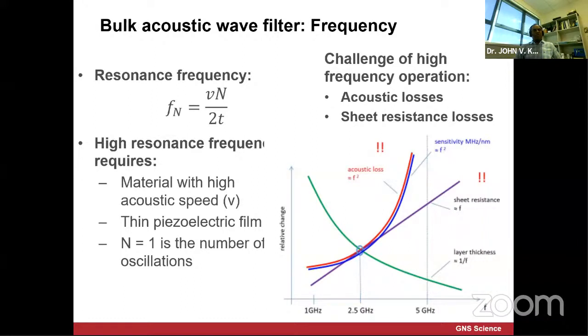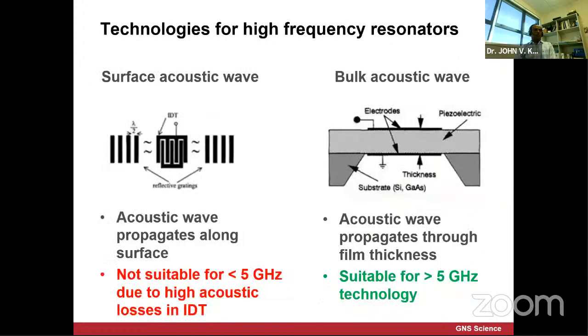This creates a lot of interesting opportunities for a material scientist to see how we can tune some of the piezoelectric material properties to reduce the sheet resistance loss and the acoustic loss, which will enhance the speed. Currently most of the simple systems use what are called surface acoustic wave filter resonators. That's the diagram there. You have interdigitated electrodes on piezoelectric materials, such as aluminum nitride and some glasses. This acoustic wave propagates along the surface, which is why it is called surface acoustic wave.